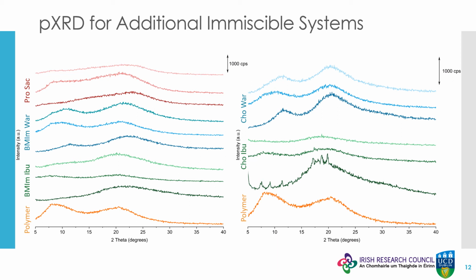Interestingly, there appear to be some small crystalline peaks in the pure co-IBU API-IL. This is attributed to the material being crystalline initially, but deliquescing as the measurement is being taken, which was also observed when preparing the material for spray drying. Nonetheless, there is no crystalline material in the spray-dried products for this example.